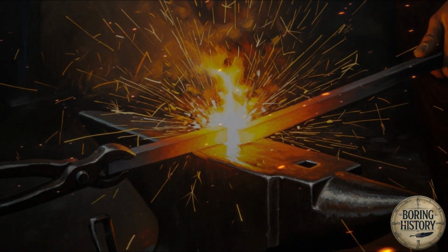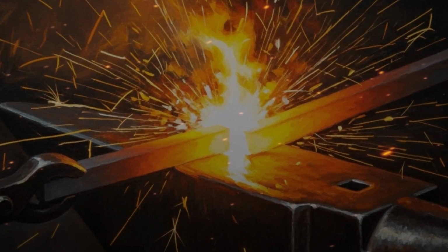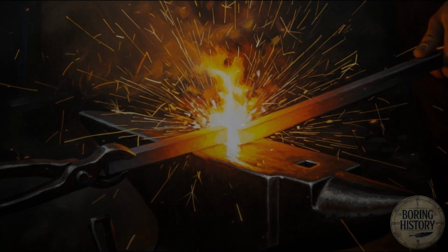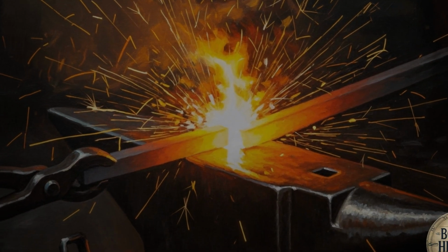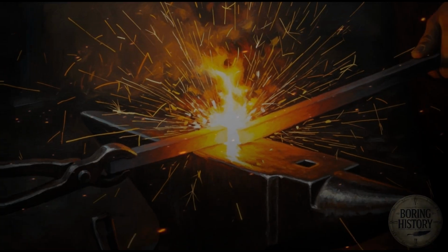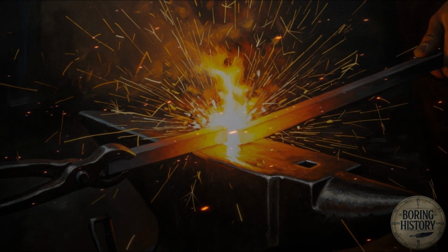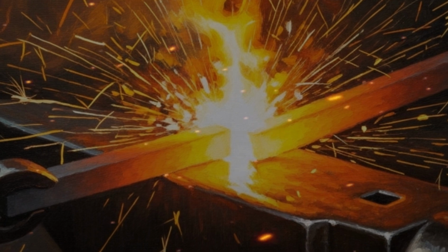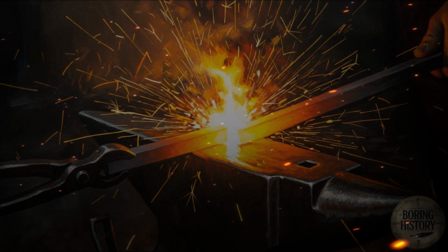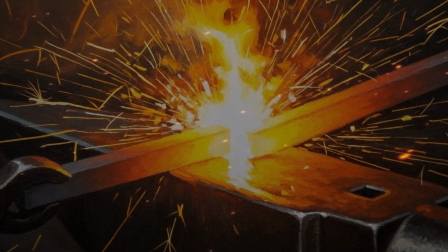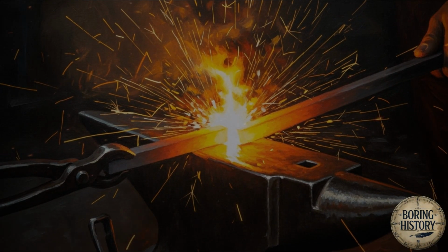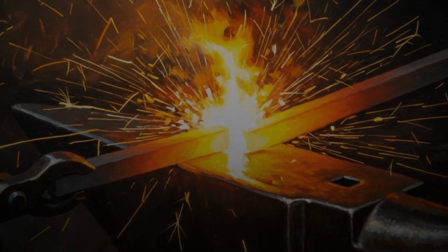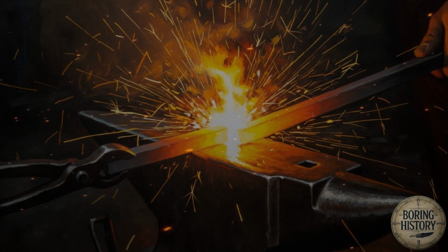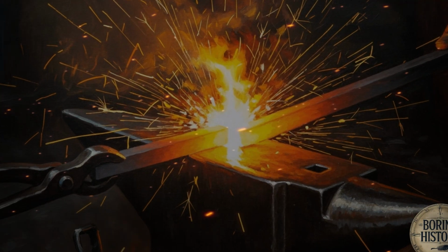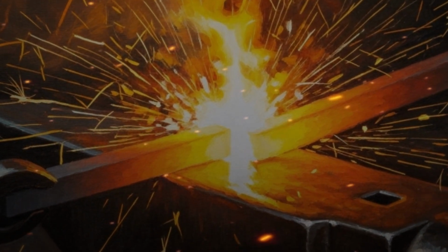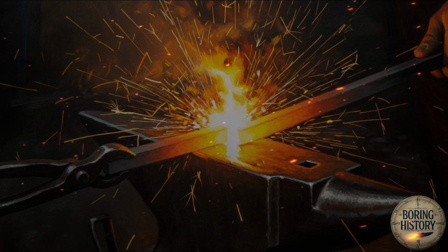"The pattern comes from the process," he said. "The craftsmen in the east, far east, past where any of us have been, make steel in sealed clay pots, called crucibles. They heat them to temperatures that we cannot reach in a standard furnace, temperatures so high that the iron becomes liquid. At that temperature the impurities float to the top and can be removed, and the carbon which gives iron its hardness can be introduced into the melt and distributed evenly through the entire piece, not just the surface. When it cools, the result is steel of a purity and consistency that our methods cannot approach."